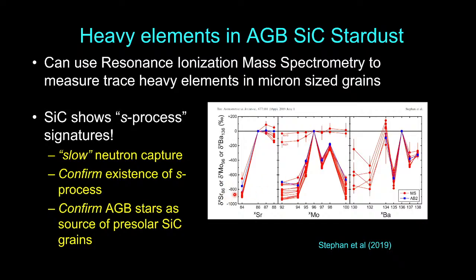And really, really low value basically means you have less of it. So essentially, all the molybdenum isotopes except molybdenum-96 are depleted. And we already thought that molybdenum-96 is basically only made in AGB stars, whereas these other isotopes are also made in supernovae. And therefore, it's not surprising that this pattern looks like this, but it also gives a very precise measurement of this pattern that goes back into the stellar models to help us better understand how these heavy elements are made by neutron capture.